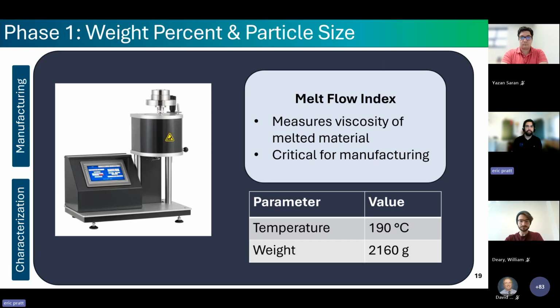Our third test was melt flow index, and this matters for a completely different reason: processability. So we need this material to be essentially a drop-in replacement for what Prysmian is currently running today. If the viscosity shifts too far from the standard, then it simply won't behave the same way on existing injection molding equipment. So melt flow index, if you're not familiar, is the inverse of viscosity. So as viscosity goes up, melt flow index will go down. And we ran this test per ASTM D1238 at 190 degrees C under a 2.16 kilogram load.